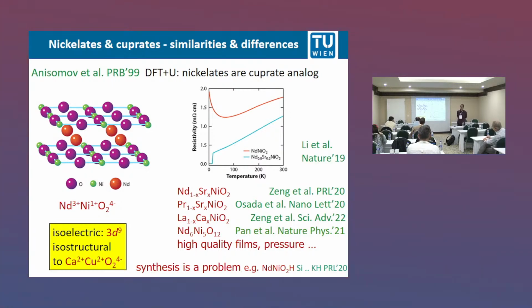It's very difficult to synthesize these nickelates, and it took 30 years before Danfeng Li and Harold Hwang were able to see the superconducting transition in strontium-doped neodymium nickelate. And then people already started to doubt, get rid of oxygen and to use hydrogen for this reduction. And then it is very easily possible that you end up with excess hydrogen, as we predicted, and the Keimer group recently has nicely demonstrated, or you can also have some excess oxygen. So these films are really prone to disorder or stacking faults, and that one has to take into account.